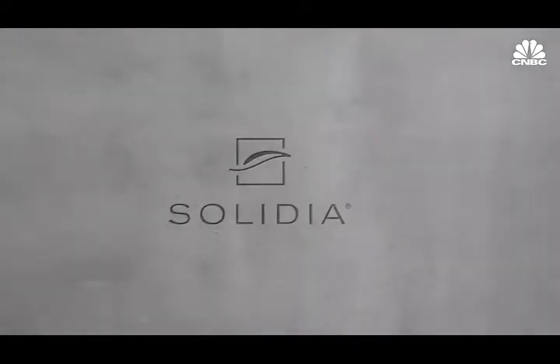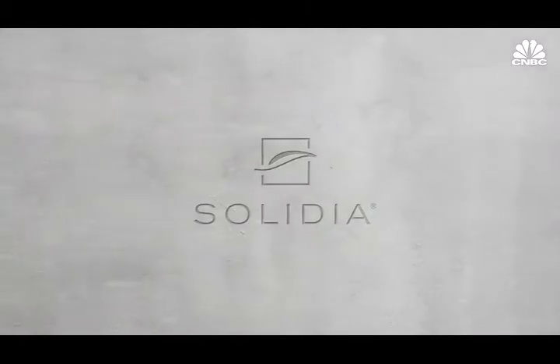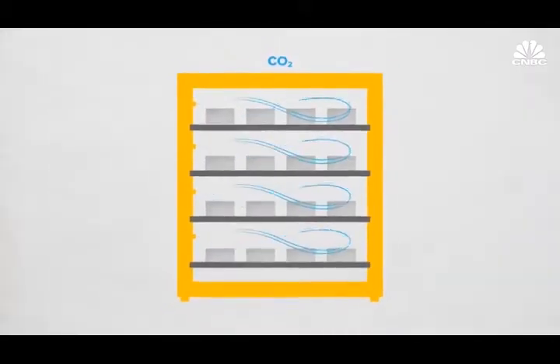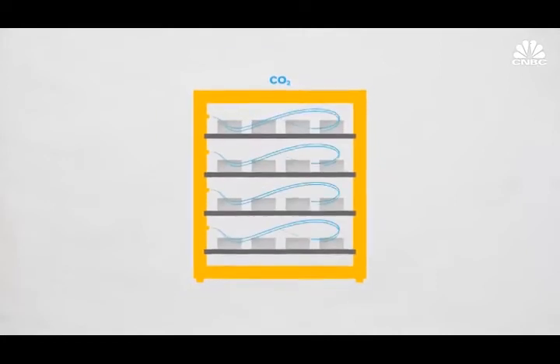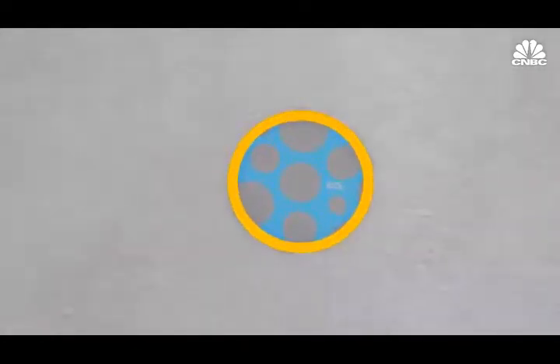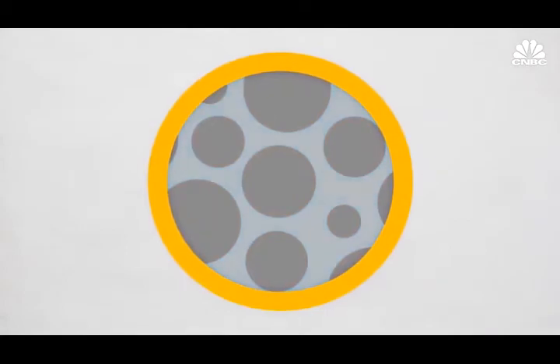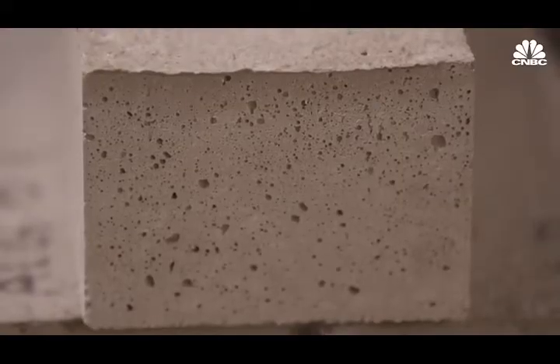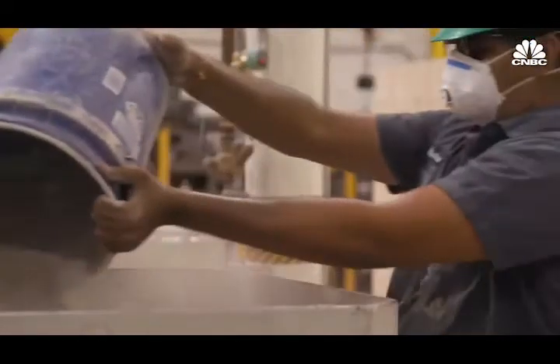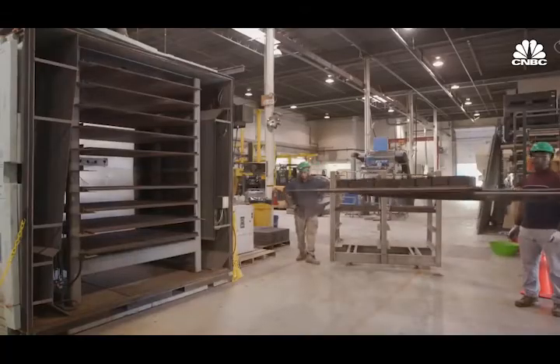Solidia cement also cures or hardens into concrete differently than Portland cement, reacting with CO2 that the company injects into a drying chamber instead of with water. As the cement hardens, the CO2 becomes trapped in the final concrete product. When you make Solidia cement, we are cutting the CO2 emissions at least by 30%. And when we cure Solidia cement, when we make the concrete, we add an additional 20-30% of CO2. We consume it during curing. So this adds up to 50-60%, and depending on the formulations, our CO2 savings can go up to 70%.